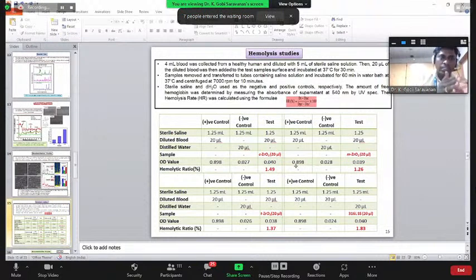But on the mechanical side, we have shown that tetragonal zirconia has the very best effect. But from a biological point of view, monoclinic as well as cubic zirconia show the higher level. In hemolysis, for monoclinic zirconia, you see the value here, about 1.49.